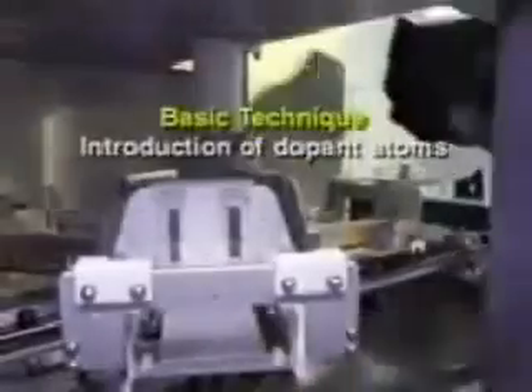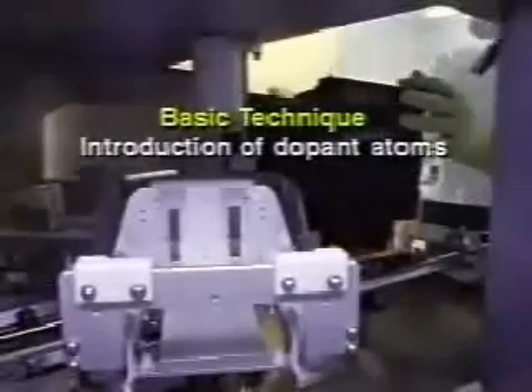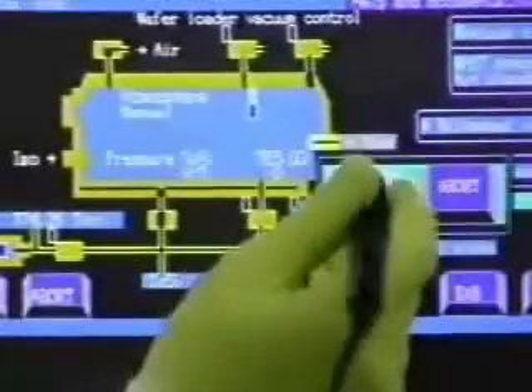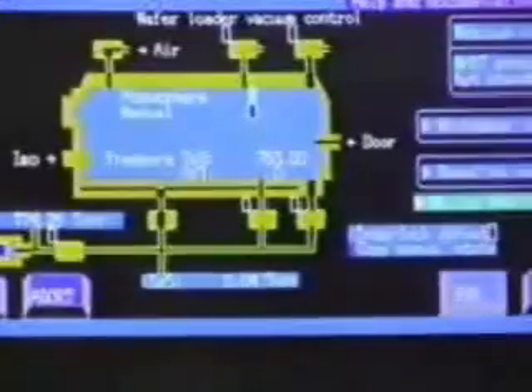In the ion implanter, dopant ions will bombard the wafers to create N-type regions. The depth of the ion implantation depends on the amount of energy used. Dopant ions are separated from other elements and accelerated to high velocities in a strong electric field. The ions are then driven into the wafers, implanting the exposed silicon regions. The silicon dioxide layer on the wafer blocks the dopants from unwanted regions.